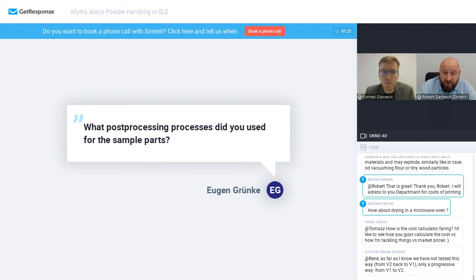What post-processing did you use for sample parts? Well, we only cleaned the part printouts and sandblasted them. Basically all those parts. If you have rubber material that is colored, we just dye it. But for PA11, PA12, all Flexa materials, we just took them out from the print cake, cleaned them, sandblasted them with the Sandblaster Extra Large, and they are ready. And the surface is just the surface that is printed.